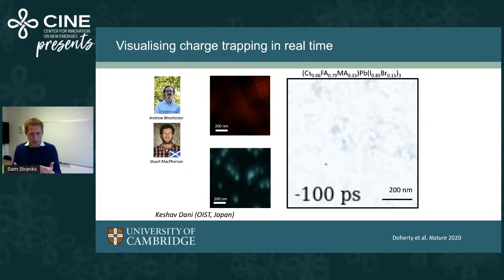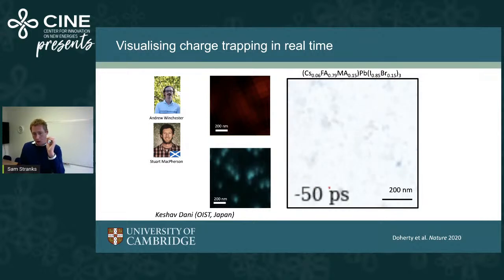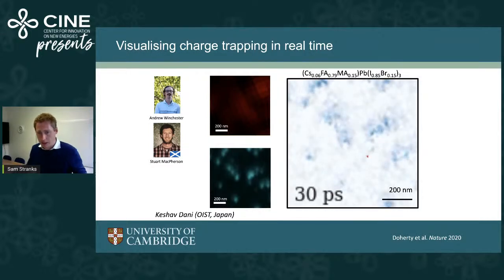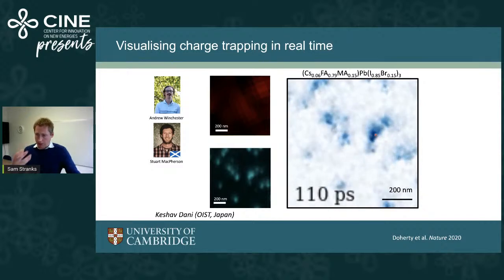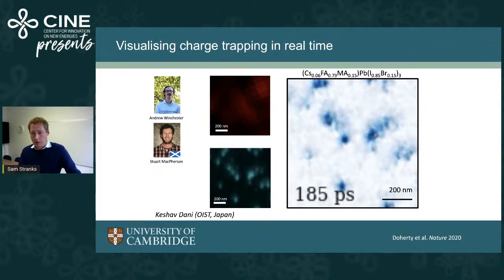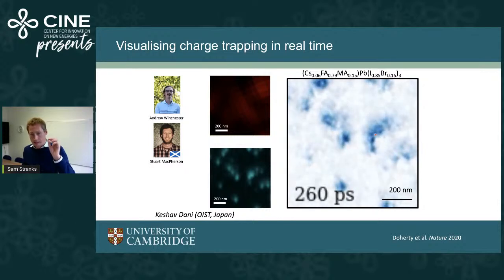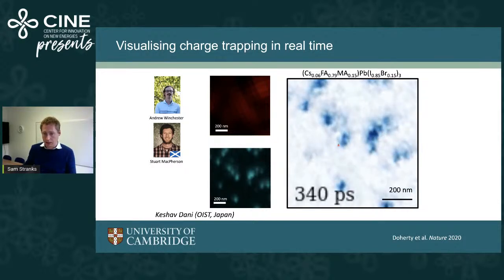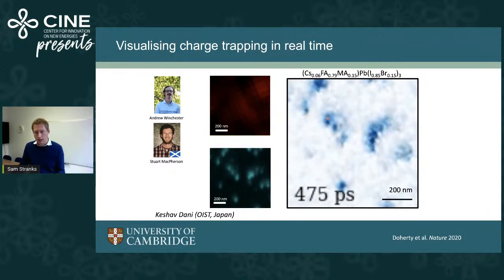Because in this microscope, we can also optically excite these materials, again with a pulse of optical light, and then we can come in with the PEEM probe, the UV probe, and actually look over time at these traps. And so I'm going to show a movie, where at 0 picoseconds, we're going to come in with an optical pulse. And then what you're going to see is the color changes. So where these dark regions are forming, these are actually electrons, these are holes and carriers trapping in real time. So we're actually visualizing these small trap clusters and these holes moving, diffusing around and trapping in these nanoscale regions. So it's a very, very powerful technique and a really interesting approach to visualize this.